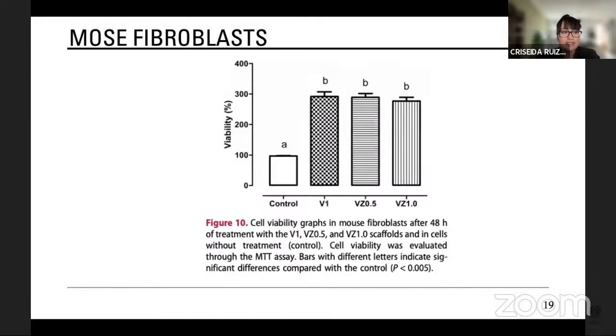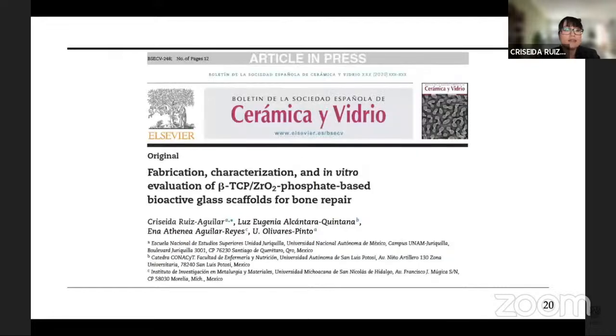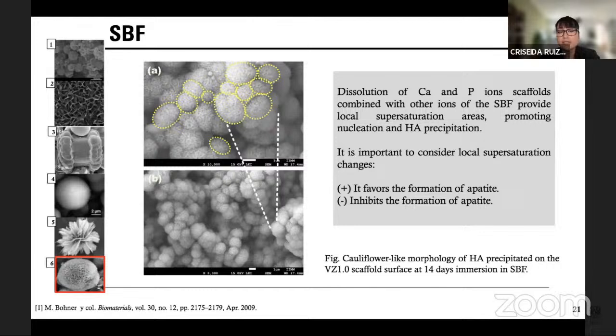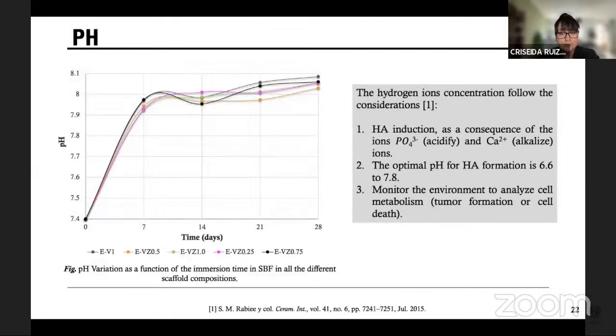In the in vitro part, the scaffolds evaluation was carried out with fibroblasts to analyze the cell viability, showing a greater increase in the cell viability in the porous scaffolds than in the control sample. Then I want to continue showing you this article that is a continuation of the previous article. The scaffold presents a cauliflower-like morphology, which is characteristic of the mineral phase of the bone tissue. As you can see in these images, hydroxyapatite can show various morphologies depending on the synthesis method and the body fluid in which the biomaterial is in contact. The simulated body fluid, or SBF, affects the dissolution of the scaffolds and releases calcium and phosphorus ions due to the local saturation. This phenomenon generates nucleation and hydroxyapatite precipitation.